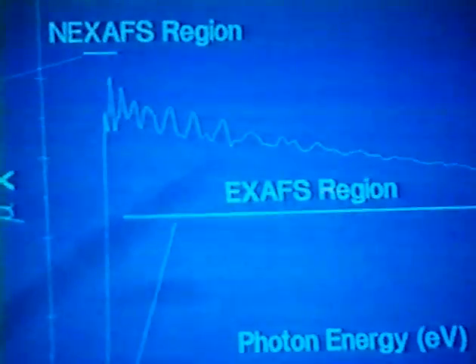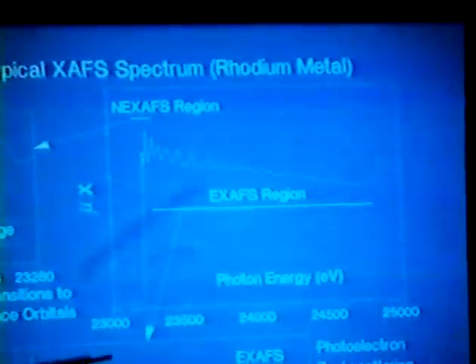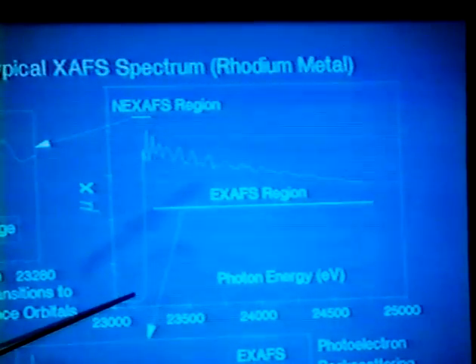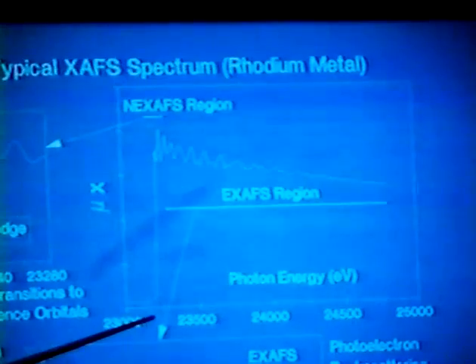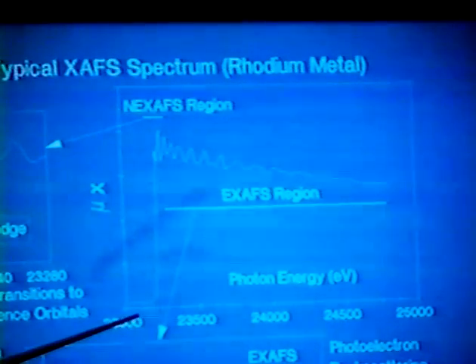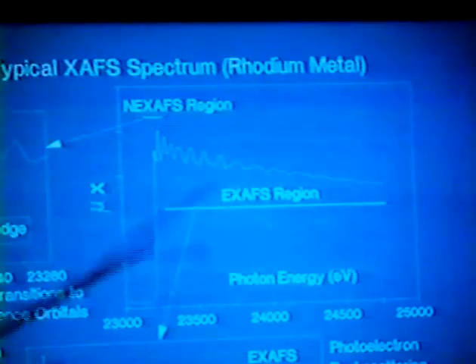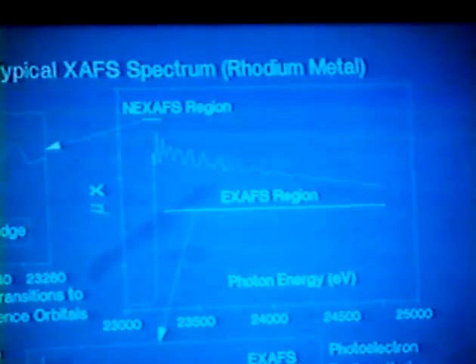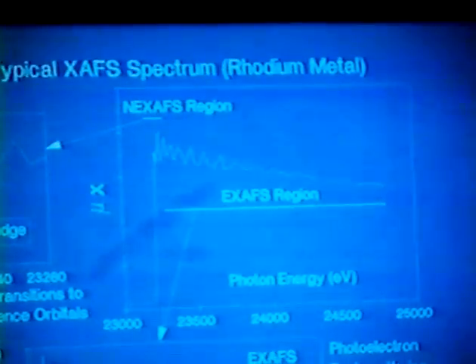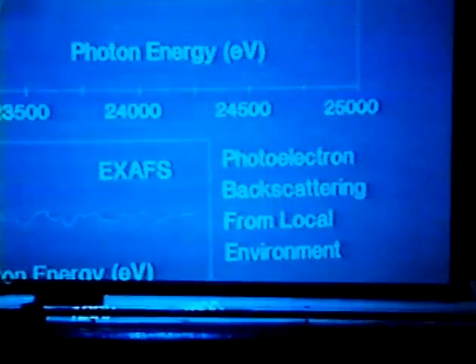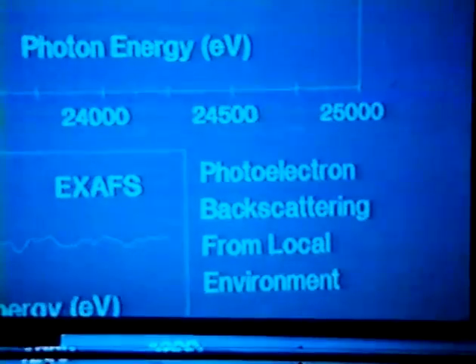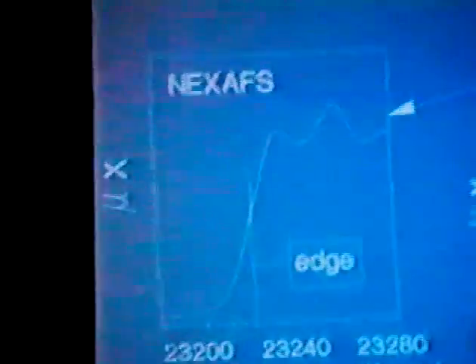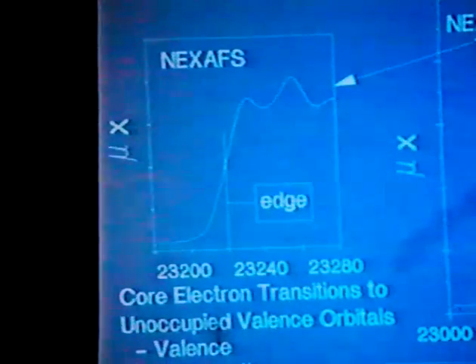This sharp increase in absorbance here occurs when the energy of the photons exceeds the binding energy of a core electron. For rhodium, this is a K edge, it's a 1s electron, and the binding energy is about 23,000 electron volts, quite high. Close to the absorption edge here, the energy that's absorbed by the core electron may not exceed the binding energy, but be very close to it, and then the electron gets trapped in some bound valence state. And so you might have some features close to the edge which are something like a map of the vacant valence level states.